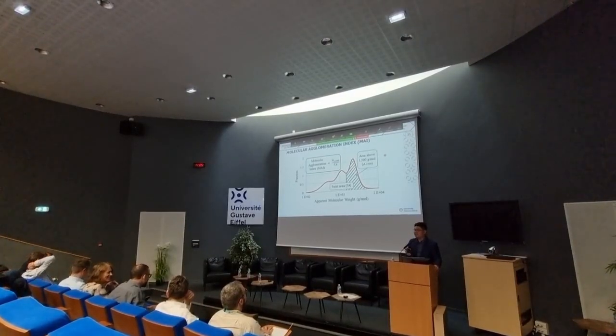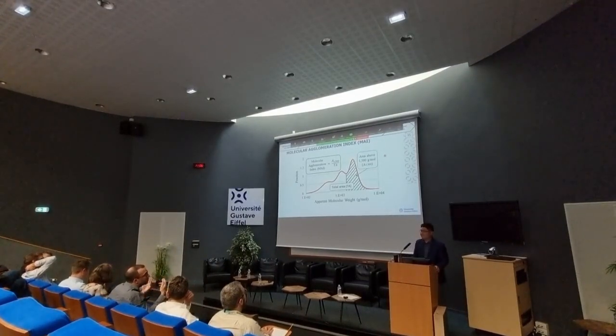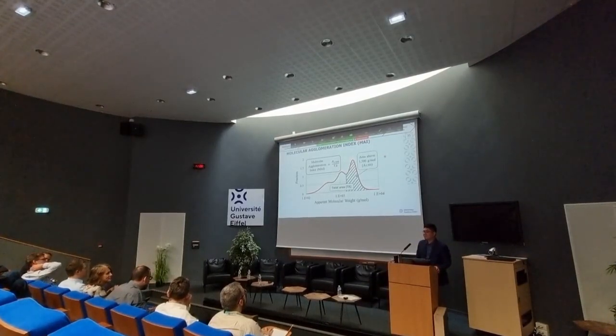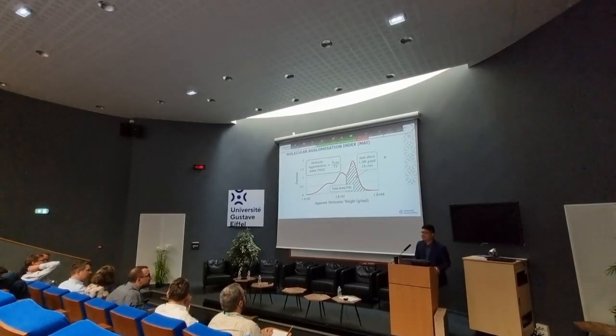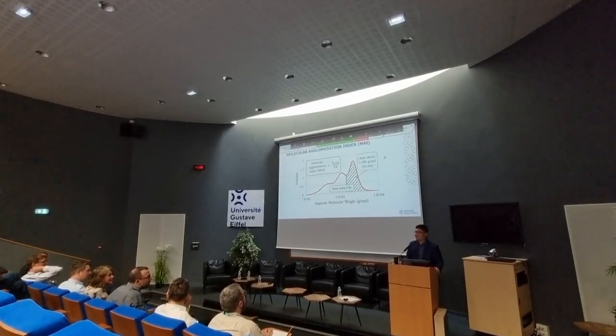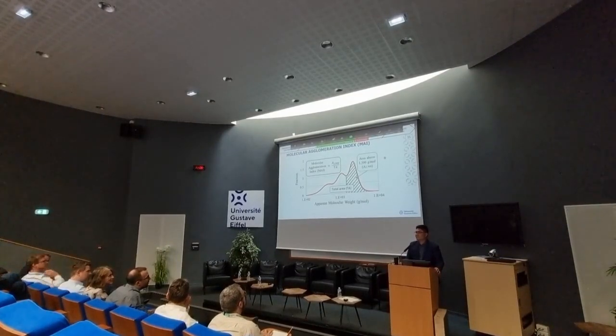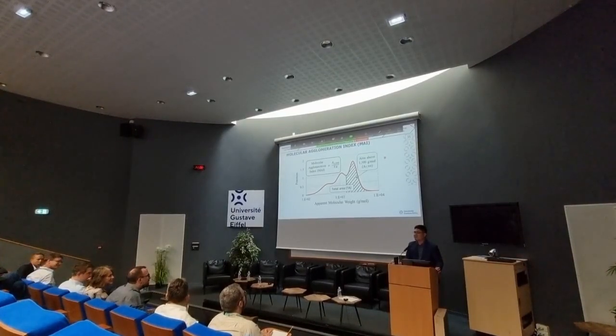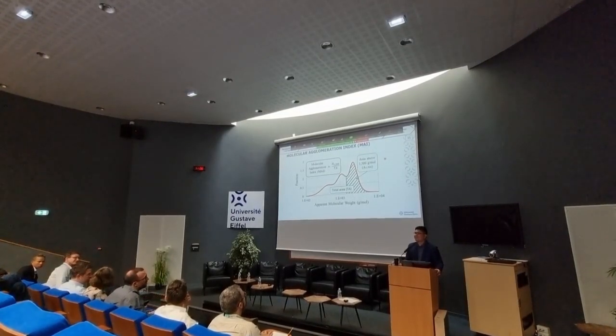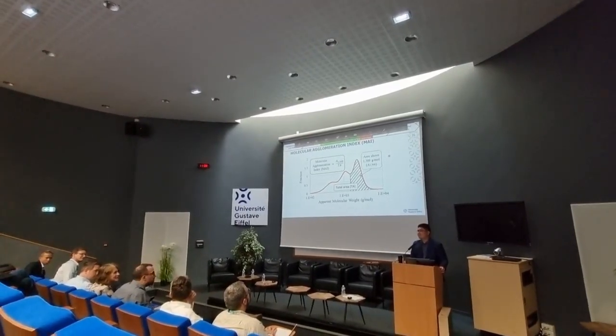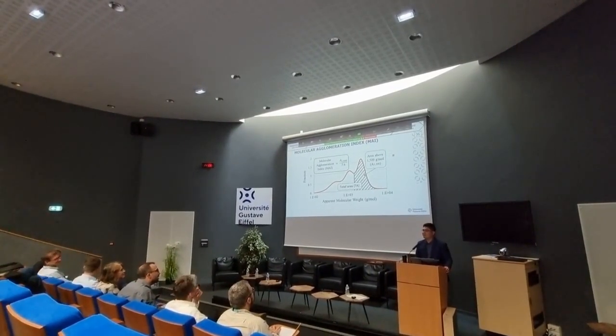you find that if you have a MAI, so a fraction of this high molecular weight and supposedly asphaltene solid particles, when you go above 0.58, you begin to have a failure. It's your failure criterion. When I see these kinds of numbers around 0.6, as a polymer scientist, I think about percolation. Gelation. Or percolation phenomenon.